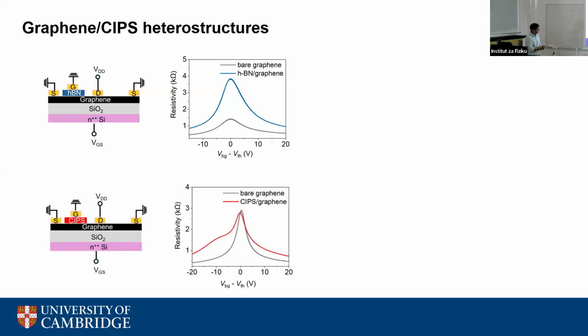But when we put CIPS, which is the ferroelectric, interestingly, we observe that apart from this main Dirac peak, we observe a shoulder peak at around negative voltages in graphene. Now, we're not the first people to see a second peak like this. What this indicates is that when you're in the negative voltage range, which means when the graphene is carrying holes, you see an additional peak, which means the graphene must be doped with electrons. So you form a p-n junction in graphene. You can see that the CIPS does not cover the entire graphene channel. So we think underneath the CIPS, it is somehow changing the local doping environment. And the regions outside the CIPS are still p-type, so it forms kind of a p-n junction. You see this additional peak.